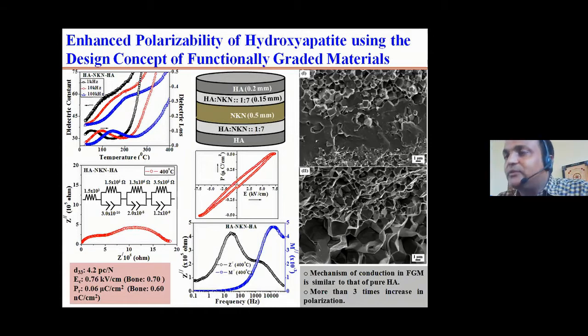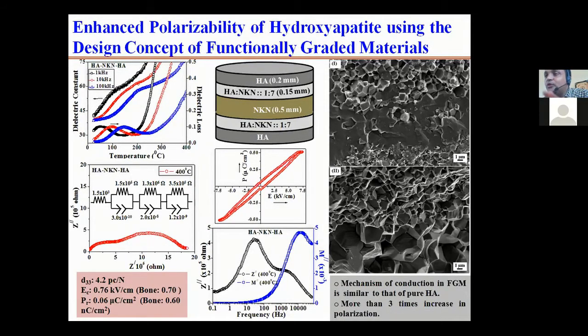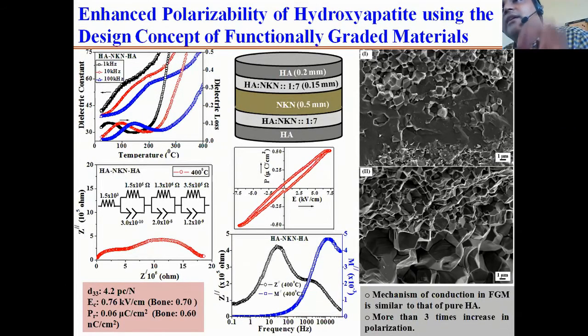Okay, so in this way, we have not seen any type of delamination or any signature of adverse effect of their different coefficients of thermal expansion. So that's why it is being claimed that spark plasma sintering is one of the best ways to obtain functionally graded materials. Not only this, hydroxyapatite as such is an insulating material, not electrically active at all. Bone is an electrically active tissue.